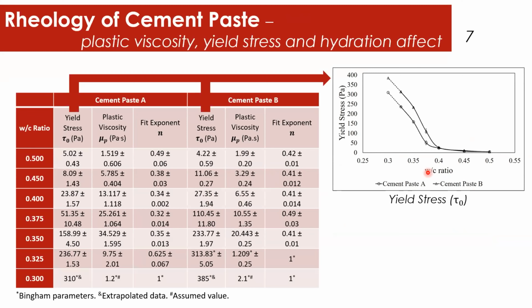Bottom line is, when I plot yield stress versus water to cement ratio, I see these two beautiful curves with the aging effect. So if we age for 30 minutes, the material is rather stiffer than the material that is not aged. However, for a water to cement ratio above 0.4, there is really no effect of aging for a period of at least 30 minutes.